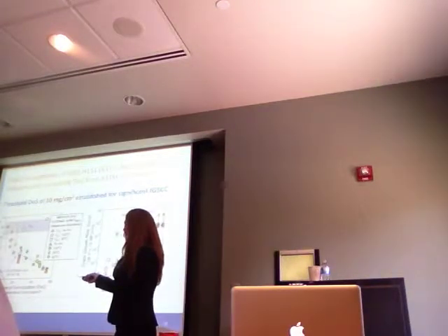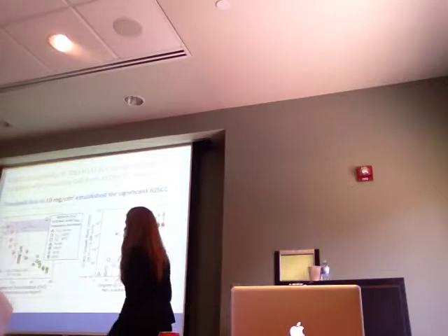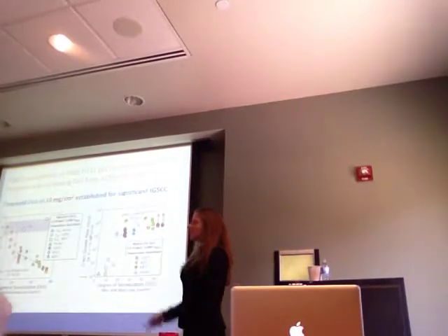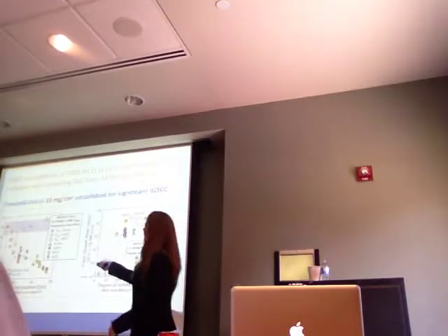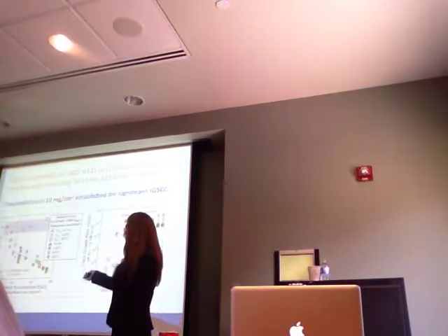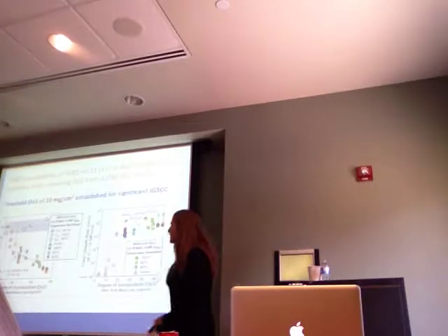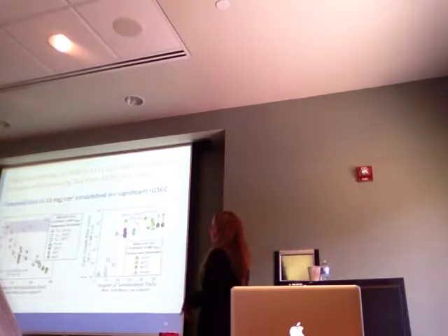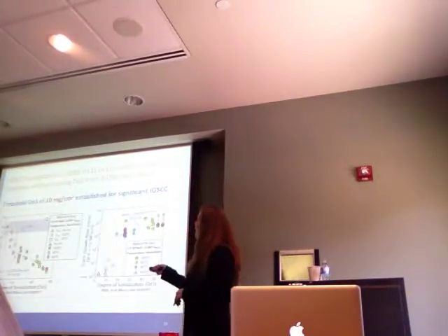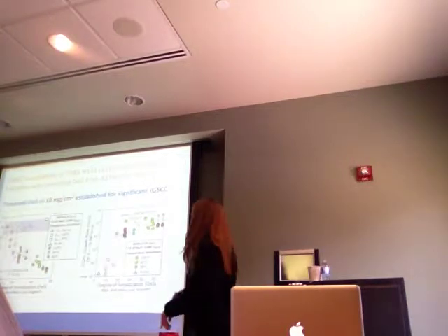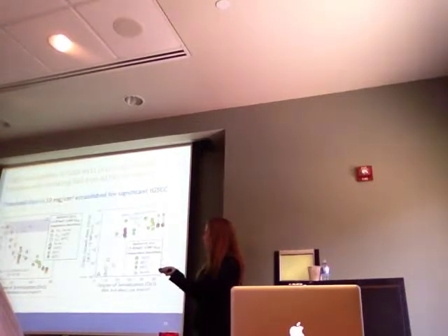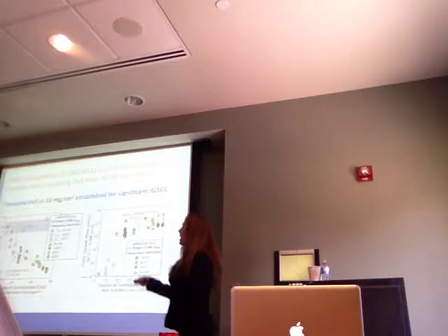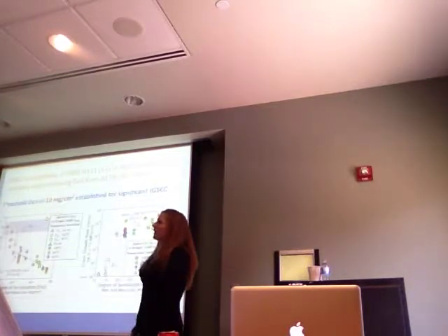Once you increase that DOS level, you can see that you drop the threshold stress intensity severely until a point about 10 milligrams per centimeter squared DOS level, where you start to see the step function and your threshold stress intensity continues to decrease as a unique function of DOS. And now the important thing to note is that we did this for 3 different temperatures, and all 3 of these temperatures fit this correlation.